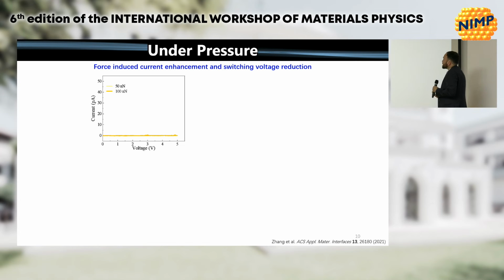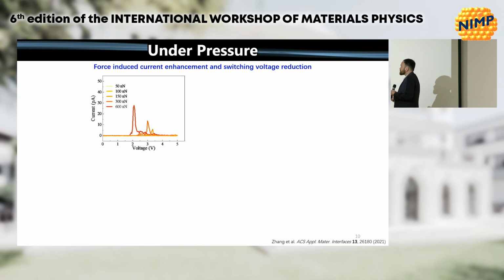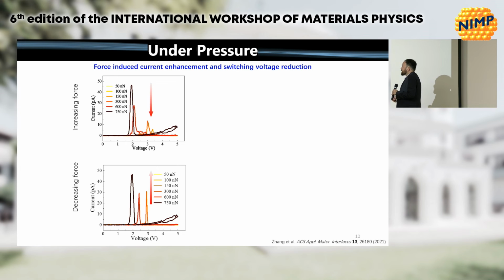Okay, so again, I've already shown this, but showing what happens as a function of force, we're increasing the force. You can again see both the peak magnitude increase and shift to lower switching voltages. And that's as we're increasing the force, but it's reversible. When we decrease the force, the same thing happens.